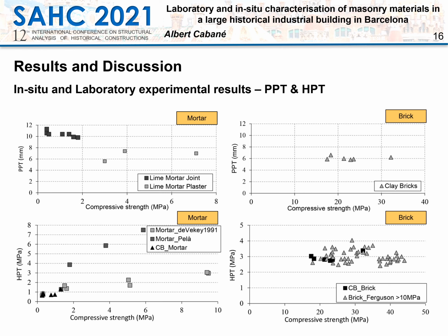In the relations obtained in this research, we could observe that the in situ evaluation of the mortar strength shows a possible trend correlation with experimental laboratory results. However, the evaluation of the bricks does not show enough sensitivity.